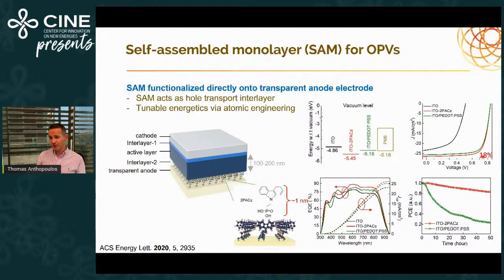we're able to achieve OPVs with a power conversion efficiency of 18%. And as you can see, it's not just the overall efficiency. We gain current compared to PEDOT:PSS. This is not surprising because we're suppressing parasitic absorption. You can see how the current increases across the EQE spectrum, but we also improve the stability of these devices. This is a very hot topic right now because, including data from our laboratory, depending on the bulk heterojunction system you're using and the specific SAM, the stability can be improved or actually degraded.